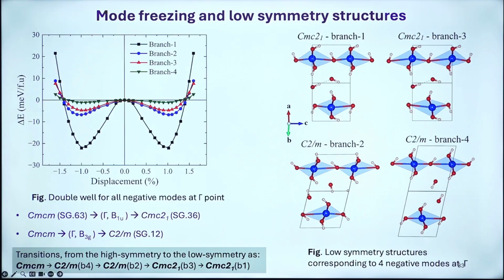We then try to freeze that particular mode. The starting point was the Cmcm structure, with the gamma point B1u mode, and when we freeze this mode, these are the branches: Cmc21 from branch 1, Cmc21 from branch 3, then C2/m, and another C2/m. So these are the 4 space groups we got by freezing the phonon mode as a function of displacement. We move the atoms and compute the total energy as a function of displacement, with positive and negative displacements, and eventually it gave us all 4 kinds of space groups. Then we computed phonons once again for those.